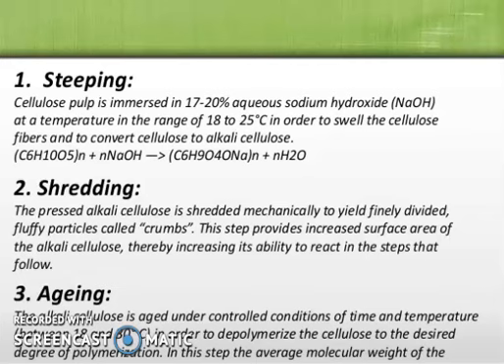Steeping is the first process. The cellulose pulp is immersed in a 17.5% to 20% aqueous sodium hydroxide solution at a temperature between 18 to 25 degrees centigrade for 1 to 3 hours. During this, the cellulose molecules react with caustic soda and get converted into soda cellulose, which is highly reactive in nature. The paper boards swell and absorb excess caustic soda, so they are squeezed. Controlled squeezing is required so that a controlled quantity of NaOH remains in the paper boards.